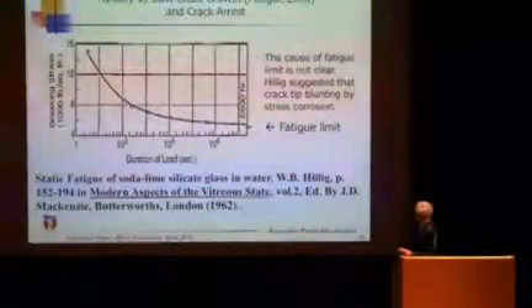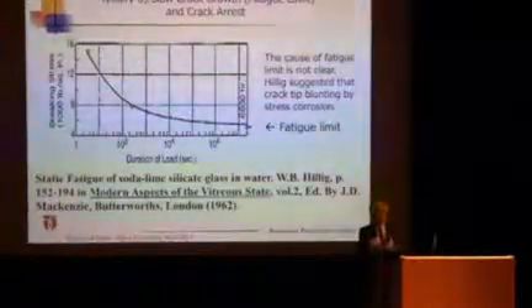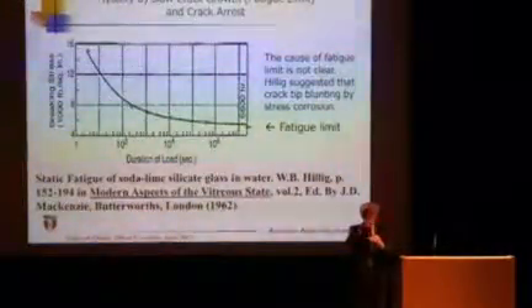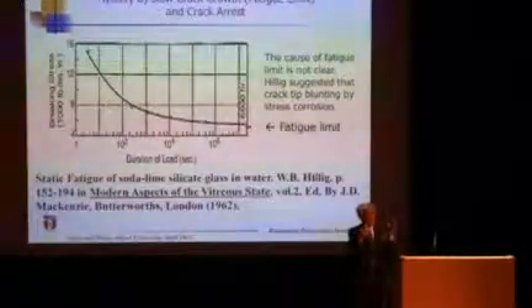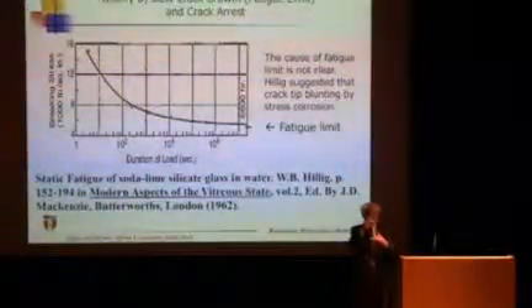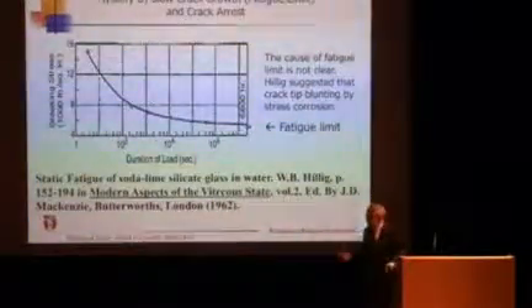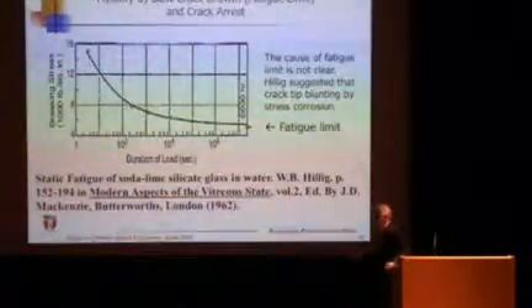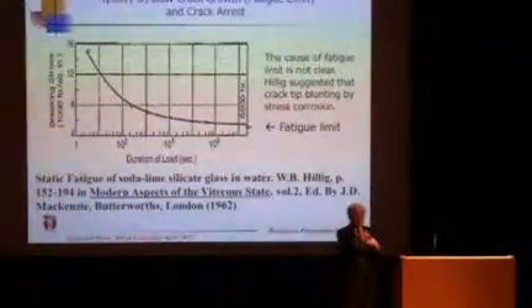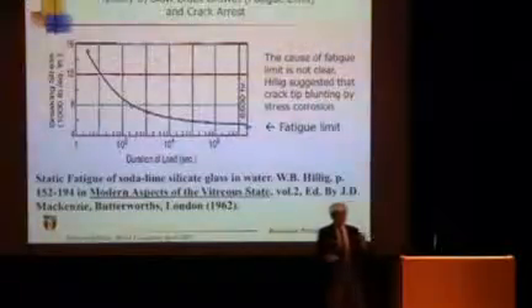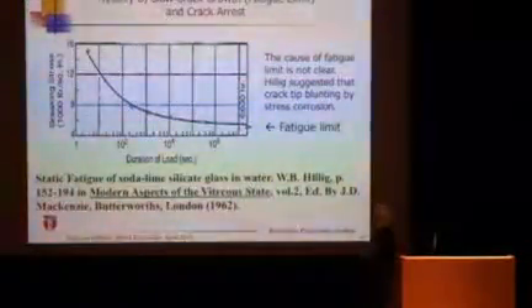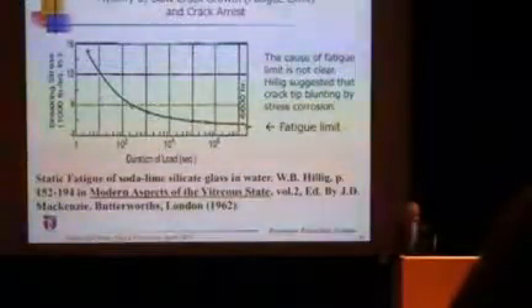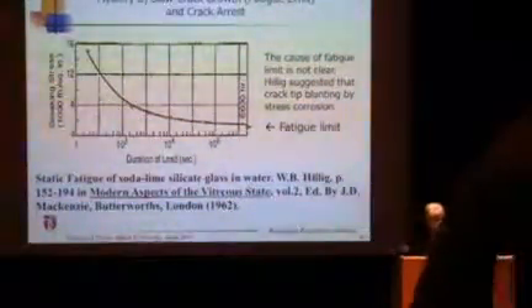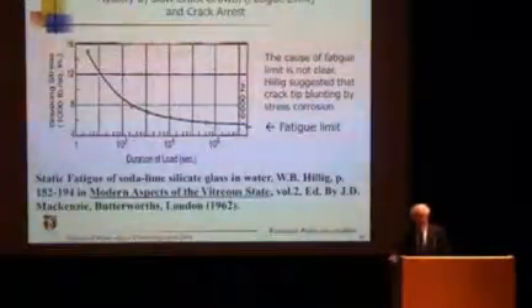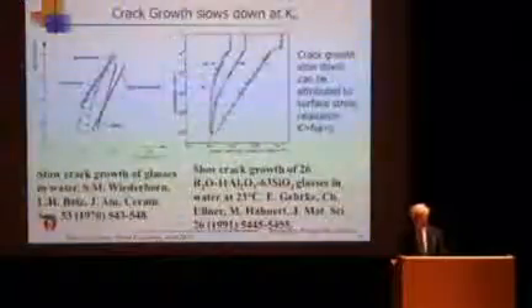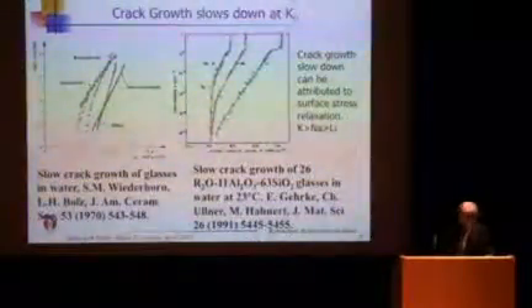And I believe this one is also due to surface stress relaxation. Under stress, near a crack tip, there's a high tensile stress, but the moisture around comes in slowly and the stress relaxes. So that tensile stress near the crack tip is reduced, especially over a long time. And when the relaxation wins out against the applied tensile stress, no fracture will happen. So first we thought, oh, this must be surface stress relaxation. By the way, lots of other people suggested different theories, but nobody seems to agree with each other. So we came up with this idea, perhaps we could explain it.